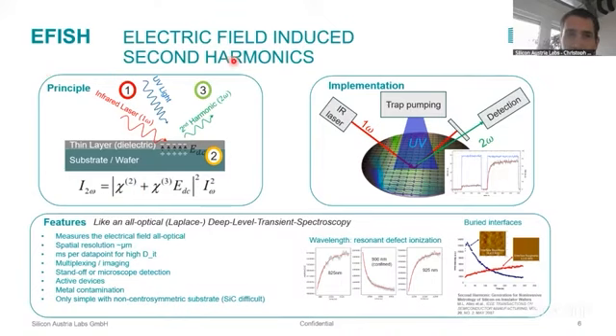And what you do is you measure basically the electric field with a laser, remote, spatially resolved, non-contact. And for this, you utilize nonlinear optics. And the use case in the semiconductor industry is interfaces, because interface quality is highly critical to many devices, also in the process development, but also on the final device.